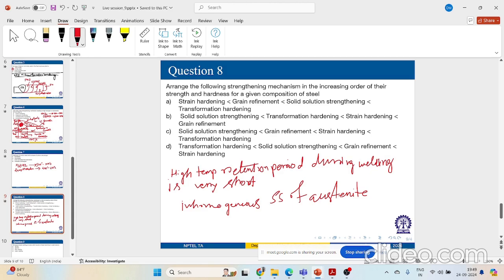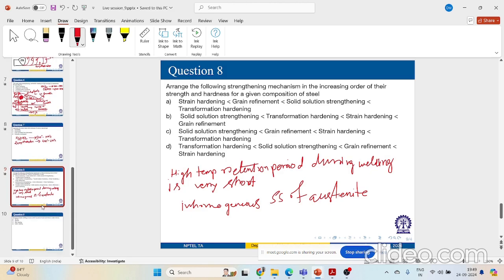While the regions that will be deficient of alloying elements will result in softer phases like ferrite, pearlite or bainite. So the region next to your fusion boundary will experience very high temperature for a very short period. Because of that, that will lead to coarsening of grain and formation of usually inhomogeneous austenite, right? So if I draw some schematic,